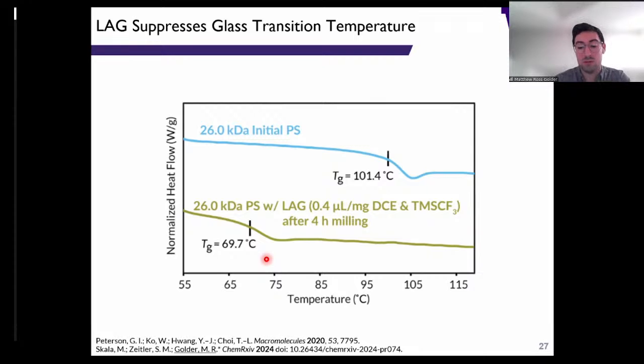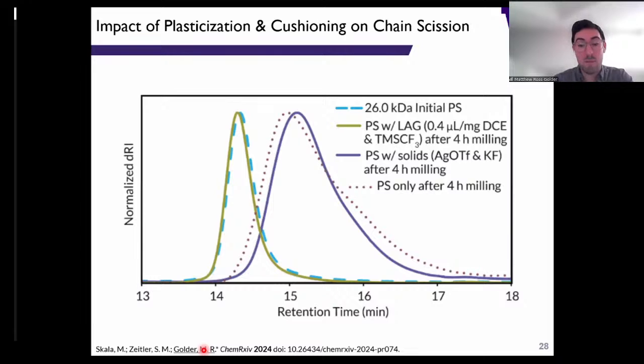this liquid-assisted grinding, and then based off of the work of Peterson and Choi, we presume that we, in turn, may be able to really cut down the rate of mechanochemical chain scission whilst still performing productive carbon-carbon bond formations for the post-polymerization modification. So thinking about this in another way, we can look at the GPC traces. We start with our initial 26 kilodalton polystyrene, so again, above the limiting molecular weight in the dotted blue line. In gold, we have the trace after we mill in the presence of our LAG conditions.